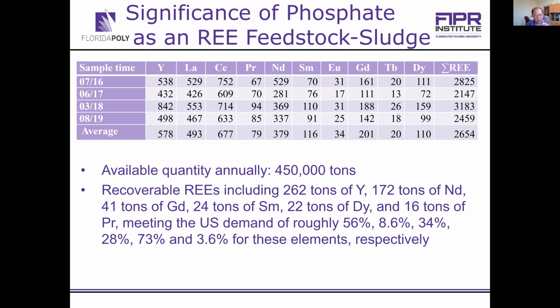In terms of volume, this shows analysis of rare earth elements in some sludge samples we collected over a 3-year period. As you can see, the total rare earth element in this sludge averages close to 2,600 ppm. It's very high, and particularly so for some of the more critical rare earth elements. Just in Florida, we generate roughly 450,000 tons of this phosphoric acid sludge. So the recoverable rare earth elements based on this table are like 262 tons of yttrium and 172 tons of neodymium.